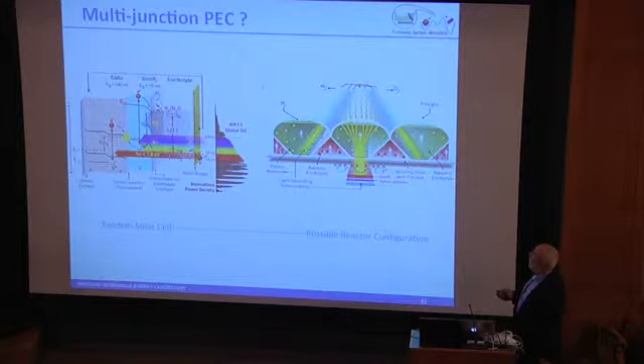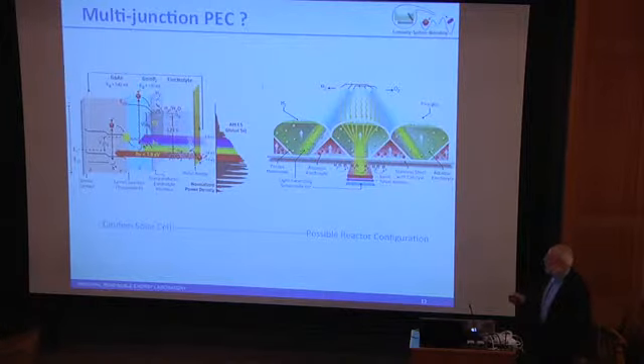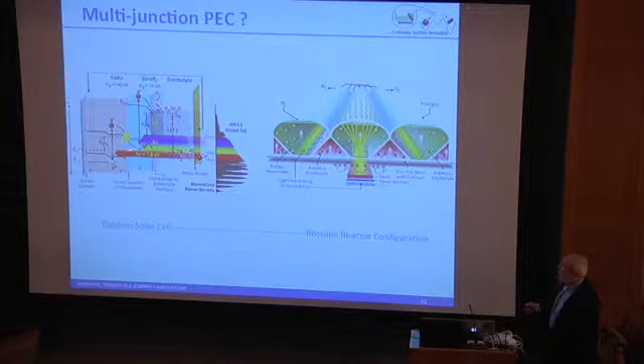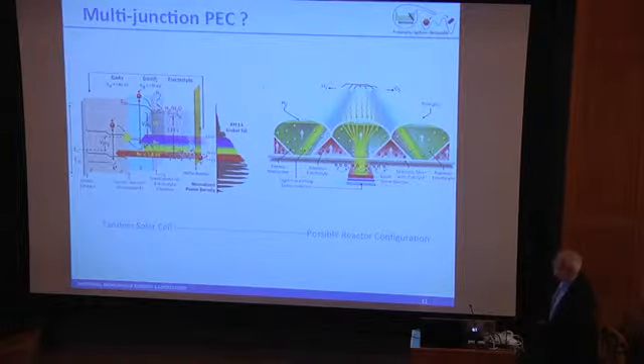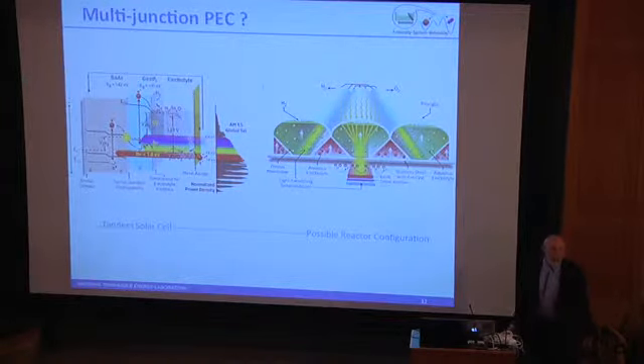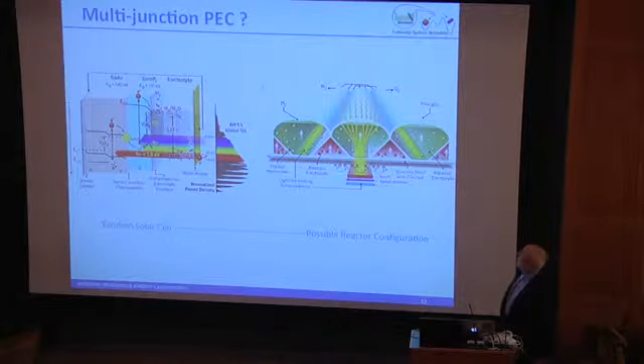I thought I would just tell you that, in reality, there are other ways to get there. I stole these from John Turner, and they're just as complex as they look. The idea is that you could use a tandem configuration, and here they use gallium arsenide and gallium indium phosphide to generate a bigger voltage. And of course, in a tandem cell, you capture more of the solar spectrum theoretically, but both of these have to have fairly large gaps. The reality is that you can get conversion efficiencies on the order of 10 to 12%, but it's an immensely complicated system, and you haven't really solved the stability at the interface problem. And so you still need to do that.